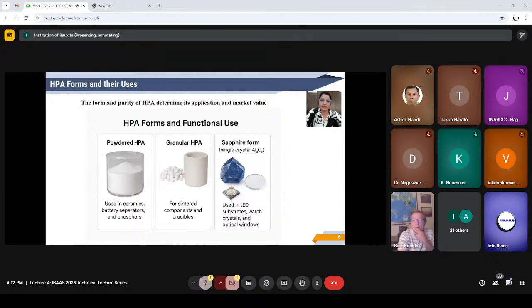Sapphire form is actually a single crystal form. When alumina is in its single crystal form, we call it sapphire. So this is one of the most well-known forms of HPA. And in the sapphire form, it is used in high precision applications, such as LED substrates, watch crystals, and optical windows. Sapphire's unique properties, such as high transparency, strength, and resistance to scratch, make it ideal for these high-tech applications. So producing sapphire requires ultra-high pure alumina, which should be greater than or equal to 4N, meaning it should be minimum 4N, and then it can be 5N or 6N as the feedstock material. So it underscores the importance of achieving extremely high levels of purity.